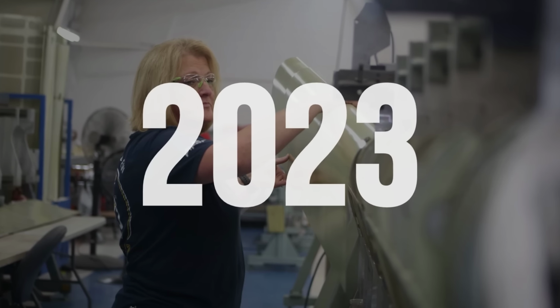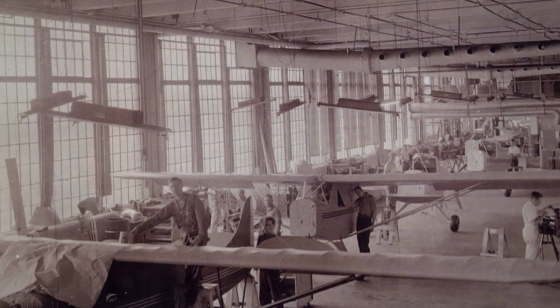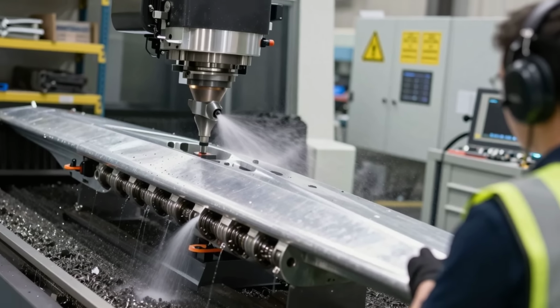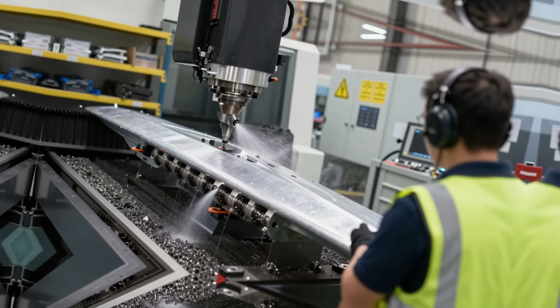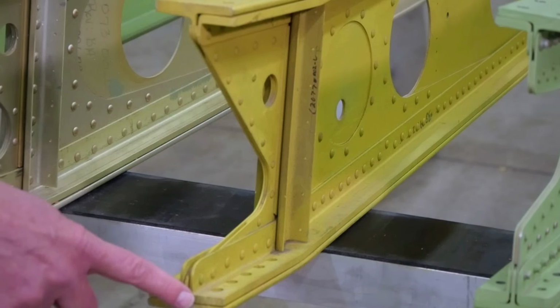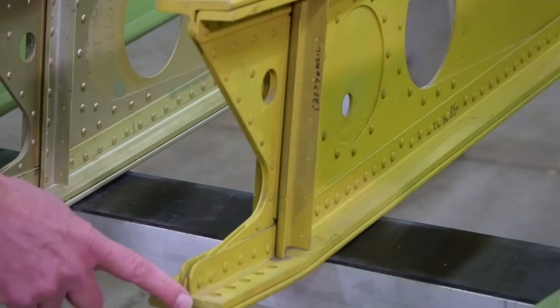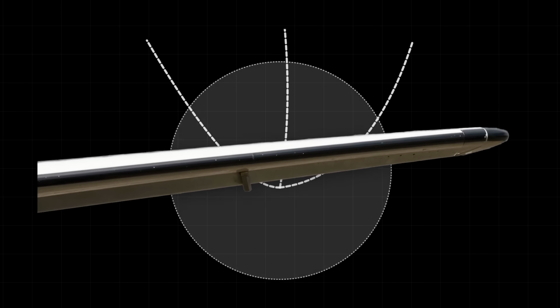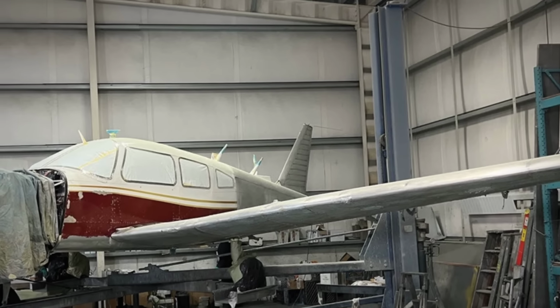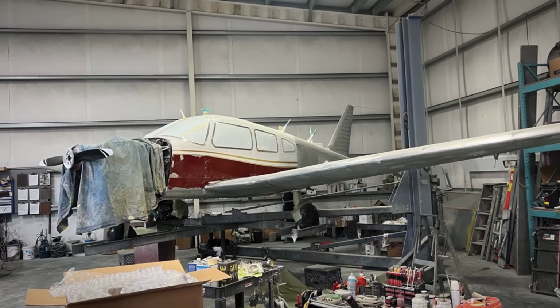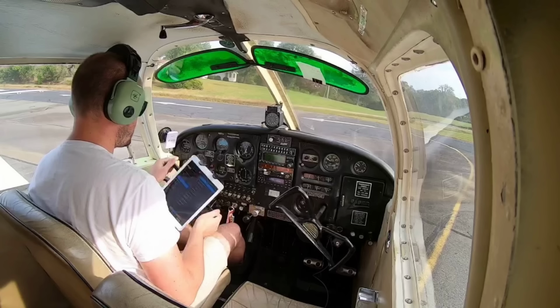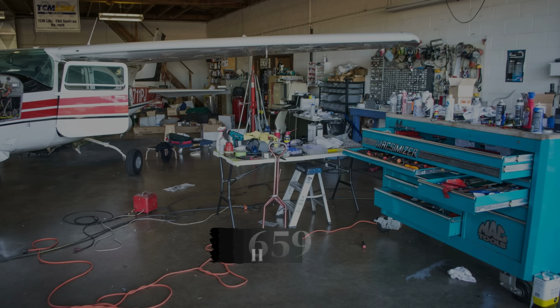The fix arrived quietly in 2023. Piper changed the production line. New spars are now machined to the final dihedral angle, not bent. The machined dihedral spar eliminates the residual stress field, drops the stress concentration at the bolt hole, and removes the life limit driver that has haunted the cold bent fleet. For owners, that means no more ticking clock, just a single 5,000-hour inspection interval and no prescribed service life.